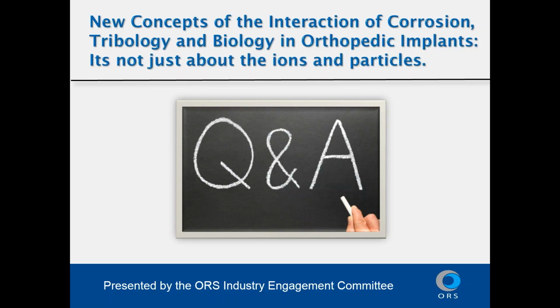Now, I should point out that oxide films don't rely on the oxygen in the solution to reform. They rely on the water to reform. So as long as there is water in the solution, there's still a possibility of oxide reforming. However, under very negative potentials that can arise from the abrasion, you might drop to or below that passivating potential, and you won't see the passive films reform, in which case you can have crevice corrosion continue even in the absence of mechanical disruption factors. And we have seen that in several cases of in vitro laboratory testing where we have driven fretting corrosion and then ceased the mechanical loading, and we've seen an ongoing current that was associated with that crevice-like behavior.